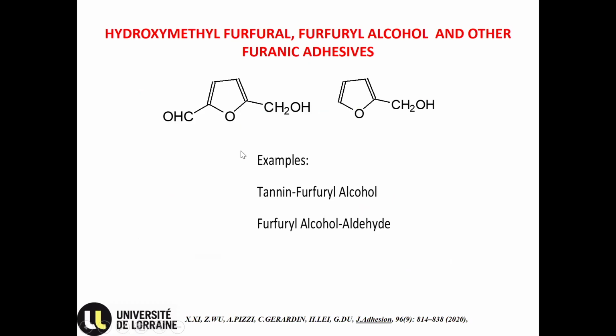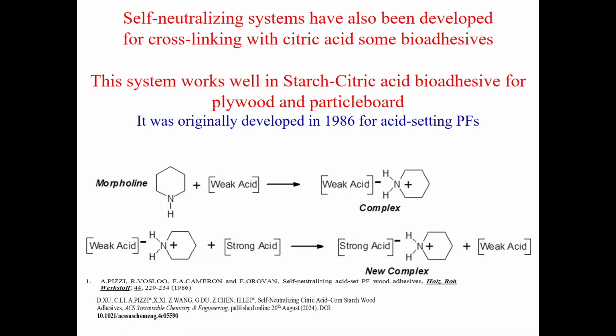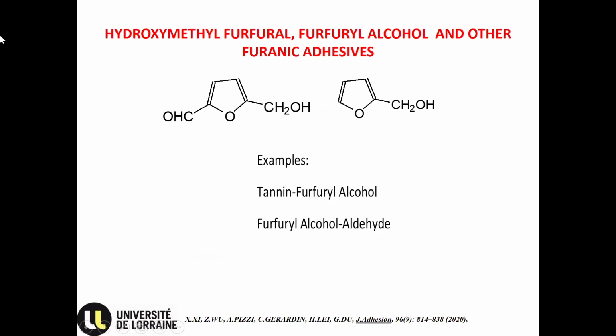The system can be used, and it has been used successfully for soy adhesives. The publication came out last year. And for tannin adhesives, so tannin and citric acid, nothing else, it is at the moment in press. It has not yet come out, but it works. It does not work with glucose because the amount of citric acid needed with glucose is too high, and the effect is not enough to bring the pH higher than 4. Then, naturally, hydroxymethylfurfural, furfuryl alcohol, and other furanic adhesives are also very interesting, and there is a lot of research being done on them at the moment.